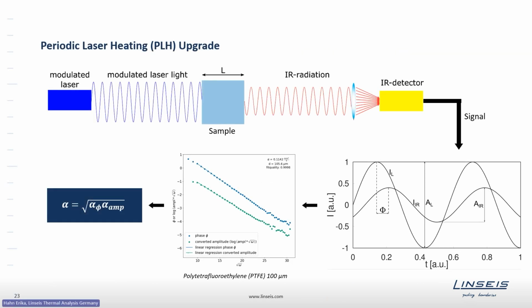Just as a rough introduction, this is how the periodic laser heating works. It has the same setup as the laser flash. So we have a laser, a sample, and on the opposite side, the infrared detector. The key difference is that we don't have this time-framed pulse towards the sample, but we now have a modulated laser light, meaning that we are working in the frequency domain. Because the laser light going into the sample is modulated, also the emitted infrared radiation will be modulated.